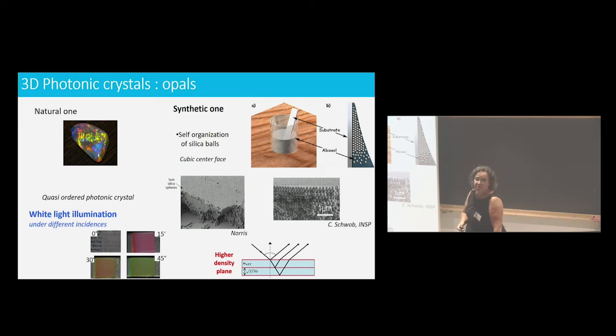In fact, as a mathematician, I like interferences. You can describe it quite easily: I have an FCC structure, and an FCC structure means that you have planes for which the density of matter is higher. So I can interpret the color, and it works quite well, by modeling a reflection on the dense planes of matter. And when you do this, you obtain constructive interference for a given incidence for a given wavelength. Of course, when you change the incidence, the wavelength for which you have constructive interference changes. And that's why you get this color.